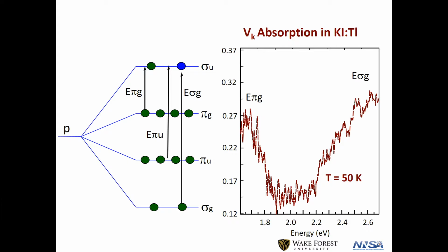And I think I even know why: it's the presence of the self-trapped holes. In basically any of these metal halides, the halogen picks up the metal electron and becomes xenon-like, a rare gas, and the metal ion gives up its electron and becomes rare-gas-like. So it's just an ionic crystal of these hard-shell rare gas atoms pressed together as tight as they can go. When you excite the valence band, you make a very reactive open-shell halogen. It grabs a neighbor, they relax together, and it produces molecular orbitals that split. This is the famous VK absorption, for example.